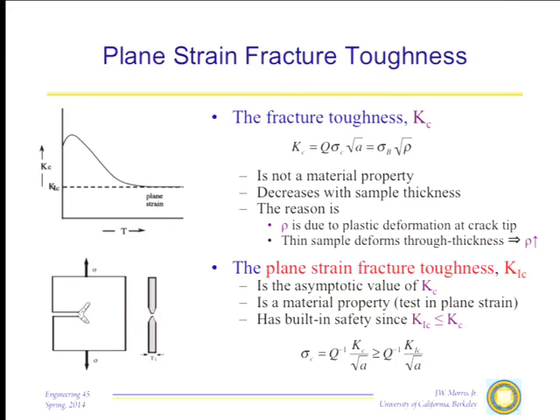Suppose I calculate that, assuming the fracture toughness is K1C. I'll get a number. To calculate the true number, I would insert the real fracture toughness K. But K is greater than K1C. So the actual breaking stress in my material is larger than the number I calculate by assuming the plane strain fracture toughness. So I've got a built-in factor of safety here. If I design something, pick the worst crack that could possibly be in there, put in the plane strain fracture toughness, and use that to find my breaking stress, I'm safe.